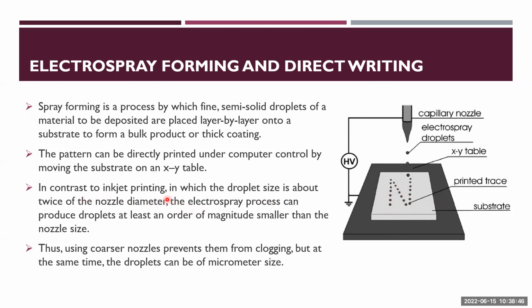A similar technology is inkjet printing. Some researchers converted inkjet printers, like HP or Canon printers, into printing cells. They encapsulated cells or printed cells using inkjet printing. But in inkjet printing, the size of the droplet is limited to the size of the printer head nozzle. In electrospray, you can go smaller than the size of the capillary. So if you are using a high viscosity solution, you cannot use inkjet printing because it will block the printer head. But for electrospray, you can use a coarse capillary because it will not be blocked by the high viscosity of the liquid, and yet you can get smaller droplets because of the high voltage you apply.